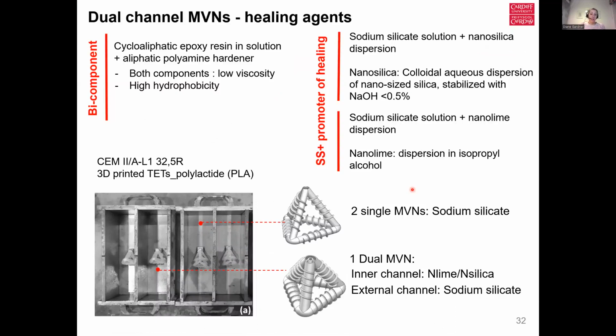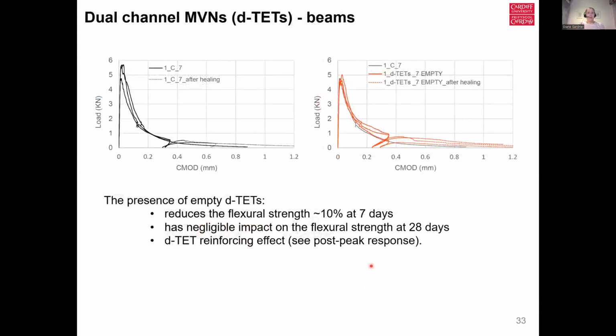We looked at combinations of two single minivascular networks with either sodium silicate and a promoter of healing in the alternative one, or a dual channel minivascular network with an inner channel with the nanolime or nanosilica and the external channel with a sodium silicate solution. And again, placed at the bottom of a mold, concrete poured around them, and then undergoing 3-point bend tests. In terms of the response, it's important to ensure that whatever we're placing within the concrete structure does not have too much of an influence on the mechanical properties of the host material.